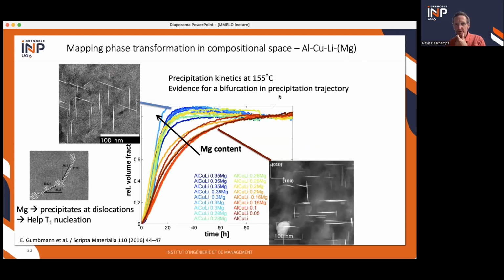Now we can do the same at a bit higher temperature. So here it's at 155 degrees. And again, you see the same kind of behavior below 0.1%. So this set of curves, you have quite slow kinetics. And suddenly, when you get above something like 0.1%, you jump to another set of curves, which are fast kinetics.